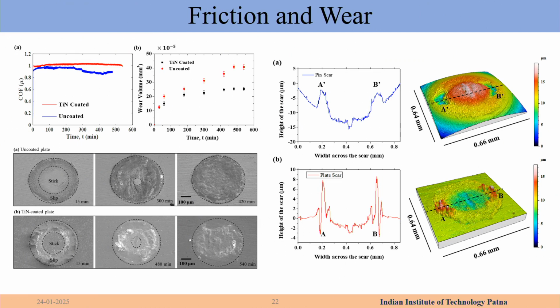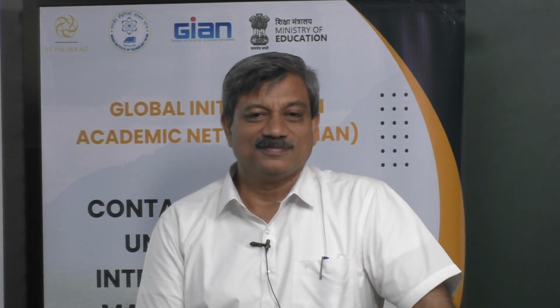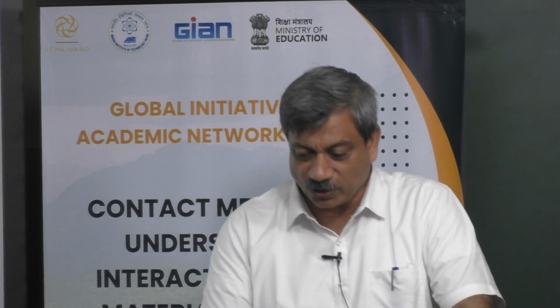Now friction and wear, this is the same thing. You can see the coefficient of friction. This is the solution now. We tried this titanium nitride. So you can see the titanium nitride coated friction is 1, okay, uncoated is lower, so the friction increases, by the way. And when you see this amount of wear volume, okay, it's very interesting. Friction is increasing, wear is going down. Friction has increased by putting titanium nitride, but the wear is going down.